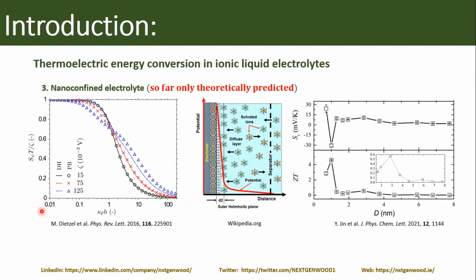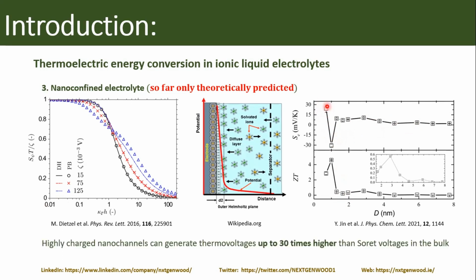There was a similar calculation recently published by another group confirming the same. So they used a different model, a different type of calculation, but they came to the same conclusion: if you place an ionic electrolyte in a nanochannel and start decreasing the width of this nanochannel, then at a certain width, which for this case is less than 2 nanometers, you have a significant enhancement of the Seebeck coefficient, which goes from something close to 0 to something like 30 millivolts per Kelvin. And from this purely theoretical prediction, we can conclude that if we place our ionic electrolyte in a highly charged nanochannel, we can expect significant enhancement of the thermoelectric effect. According to these predictions, it's up to 30 times, but of course, it's not necessary that we have exactly the same number experimentally. So we wanted to test this experimentally, and for that we needed to find these nanochannels.